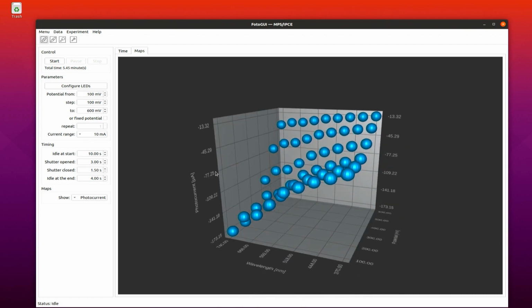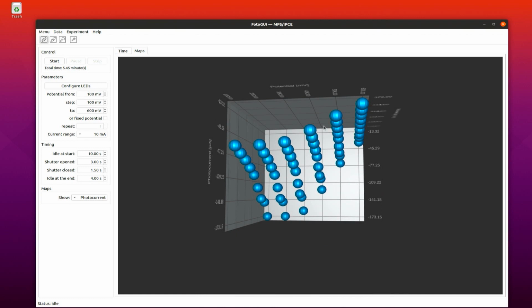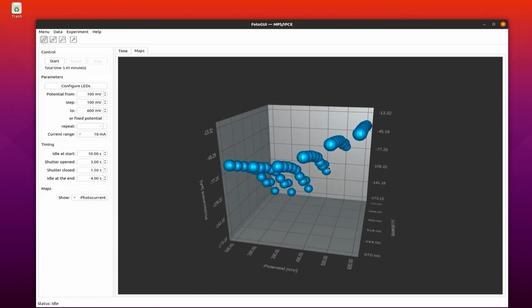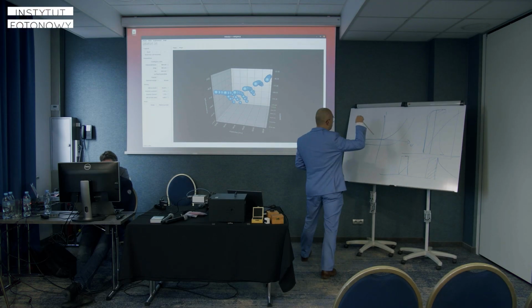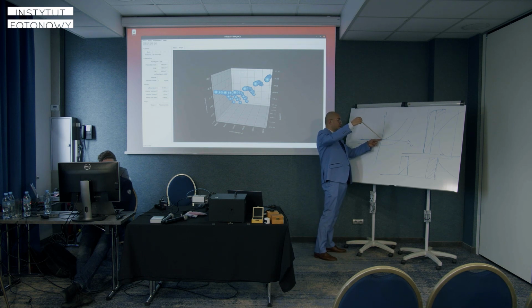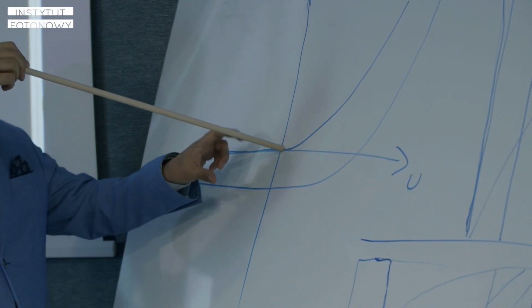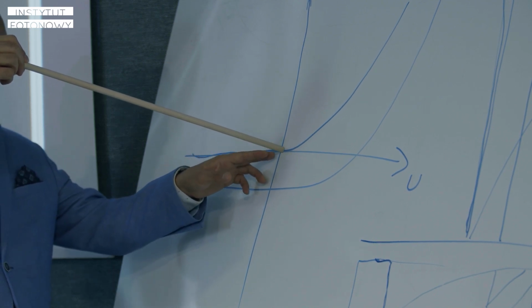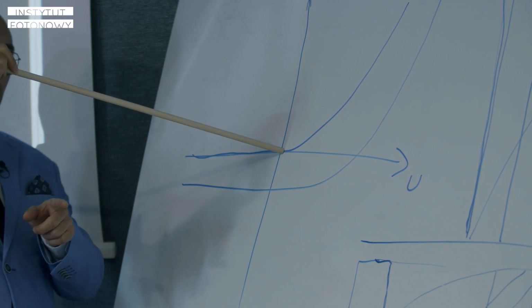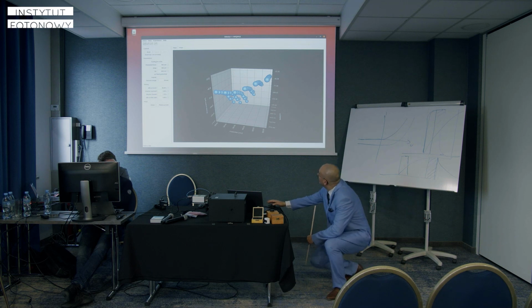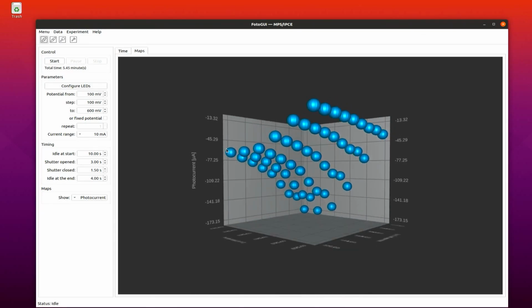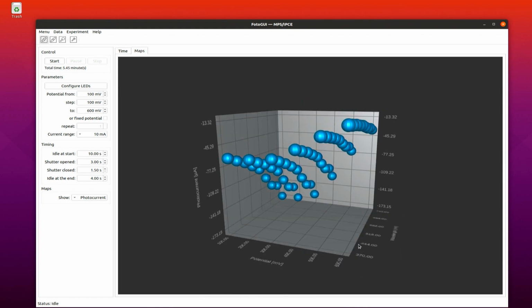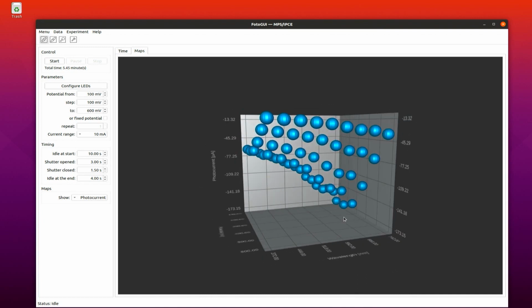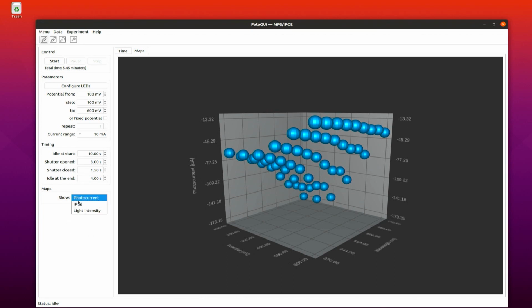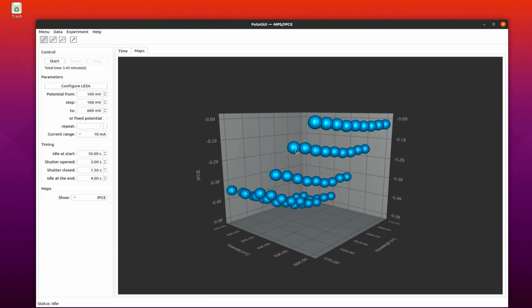And if you look at different potentials, you can also connect these points in your imagination, and this trend somehow reflects the trend in the presentation, but this is photocurrent. If we apply another axis here, photocurrent will be decreasing, because these are negative values. So the absolute value of current will increase when the light power increases. You can see this trend on this graph if you connect these points and these points: photocurrent as a function of potential, and for different wavelengths. We can express the same measurement result as quantum efficiency.